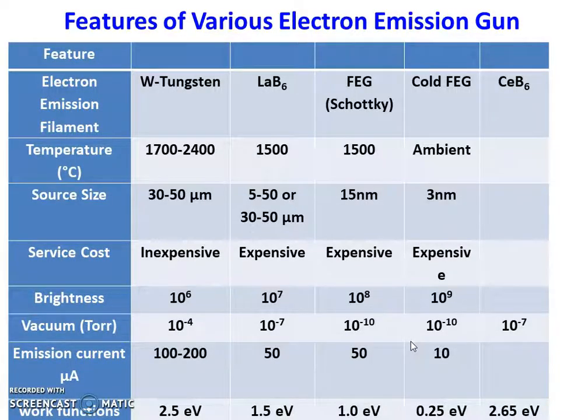If you see the features of the various electron emission guns on a comparative basis, you will find that tungsten based electron guns reach temperatures of 1700 to 2400 degrees centigrade, and sometimes up to 2500 degrees centigrade, which is really too much. In the case of LaB6 it goes up to 1500 degrees centigrade, and in the case of field emission it also goes up to 1500 degrees centigrade. But in the case of cold FEG, the electron gun temperature remains nearly at room temperature, so this is an excellent change. The source size in the case of tungsten base is 30 to 50 micron. In the case of LaB6 it remains at the same level, but in the case of FEG it comes down to 15 nanometer, which is further reduced in cold FEG to 3 nanometer.